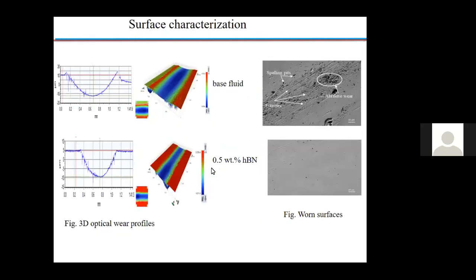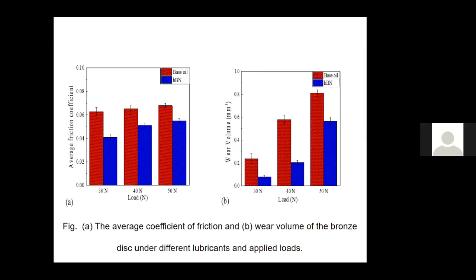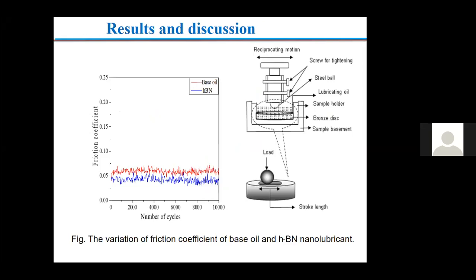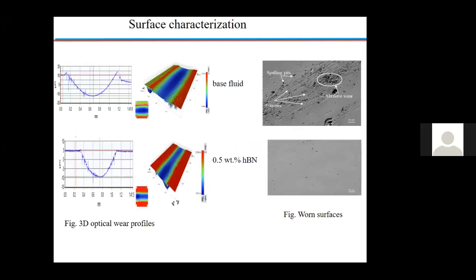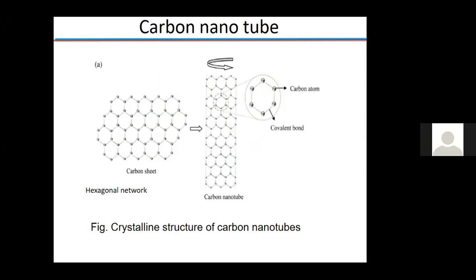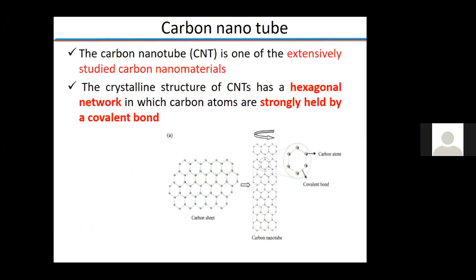This is another option. We have to go for maximum reduction in friction and wear by considering the appropriate nanoparticle. At the initial stage, we used HBN nanoparticle, boron nitride. Then we found the other option to minimize wear and friction to a great extent. For that purpose, we have considered carbon nanotube. This is the crystalline structure of carbon nanotube. These are the details of the carbon nanotube.